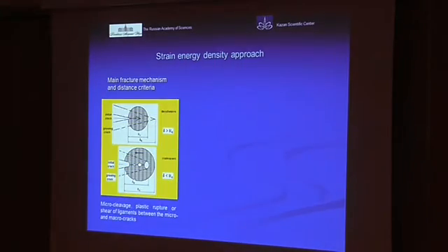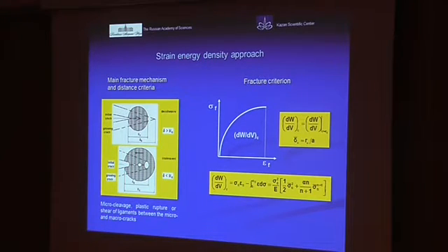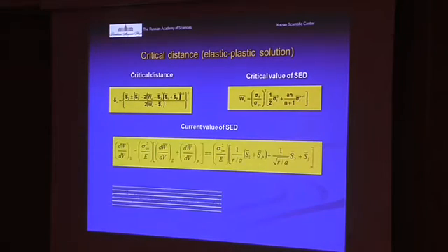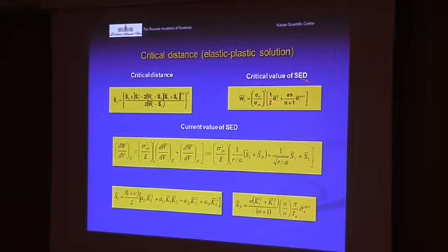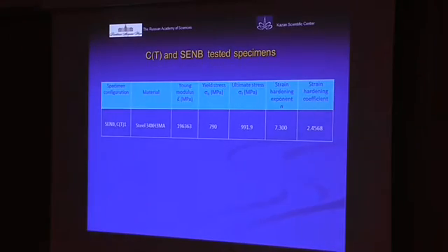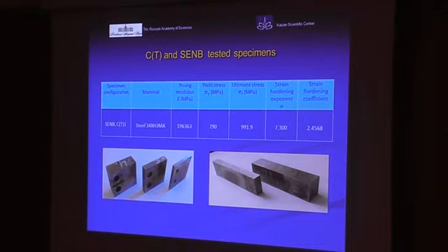To determine the critical distance, we used the well-known strain energy density approach, and now I will show you the equation to determine the critical distance. This critical distance is a function of the main elastic-plastic mechanical properties of materials and the plastic stress intensity factor. The next figure shows our experimental results.